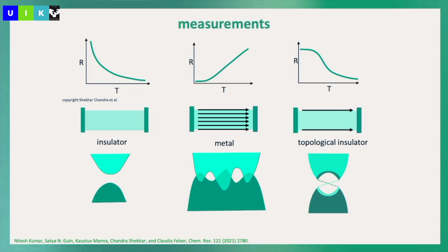Okay, so then you can measure the thing. We know we have insulators. If we measure the resistance versus the temperature for insulators, it becomes larger and larger at low temperature, because we have this electron gap here, and we need a thermal excitation to bring electrons to the conduction band. In metals, we see this typical behavior because we have a lot of electrons in the bulk. And in topological insulators, people think that the typical behavior is that you see at very low temperatures a plateau. And you will eventually see it in our measurement also, because of the surface state or the edge state.